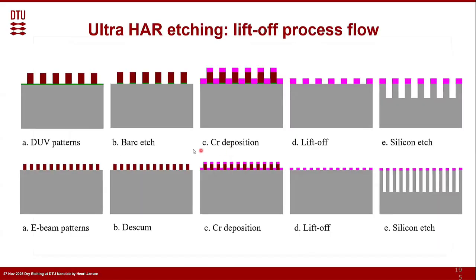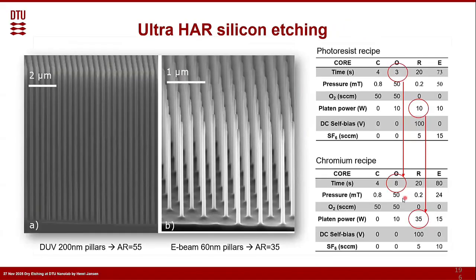What we first do is we pattern it. In this case, we do it with lift-off technique. But the end result is that we have a chromium pattern on top of a wafer, and then we're going to etch. It's either with a deep UV or with the E-beam. It doesn't matter that much. Doing so,